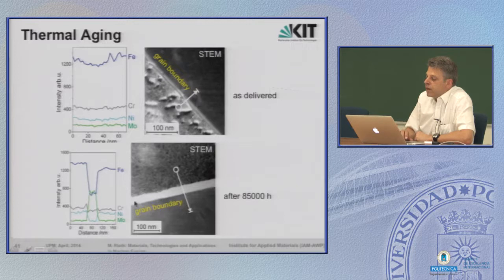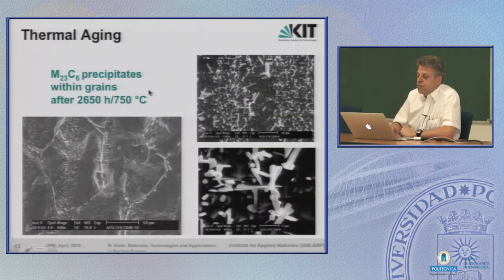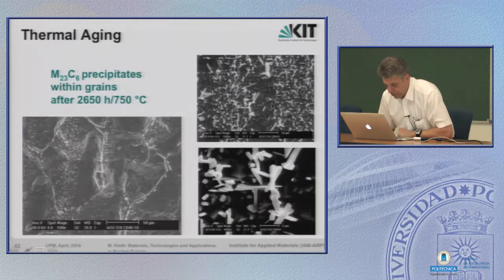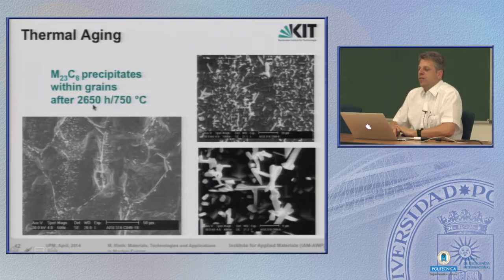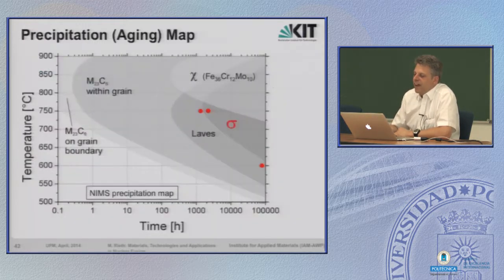But after 85,000 hours, you see the grain boundary is broader now. And if you again make a chemical analysis along this line, you see iron is lost in this grain boundary, and we have a high amount of molybdenum, at the edges some chromium. So what we have here is what is called Laves phase. That's also an intermetallic phase, which embrittles the material. Carbon precipitates can also appear within the grains. They are very many here after only a few thousand hours, but at 750 C, this is all contributing to the thermal aging.